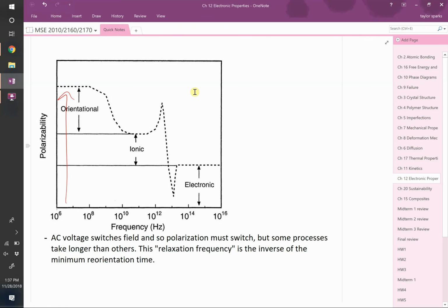And solid-state memory, there's a couple ways to make memory. One of them is literally due to that. You switch a polarization, and a little bit of it stays there. And the switching polarization is due to ions shifting positions a little bit. Which is why if you have solid-state memory and you heat it up, you delete it. Magnetic memory, it will also happen, but it's a different mechanism.